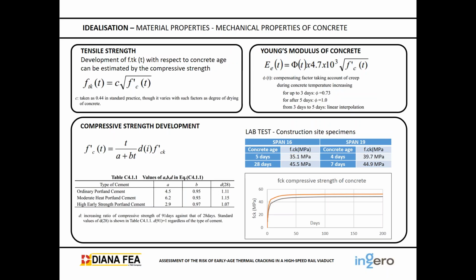Regarding the material properties, the mechanical properties of the concrete, as I have said, we have the lab tests with the construction site experiments that give the compressive strength of concrete at 5 days and at 28 days. We have here 35 megapascals and 45 megapascals. And from span 19, at 4 days we get 39 megapascals and at 7 days, 44 megapascals. So it was a very high strength cement which was placed on site.